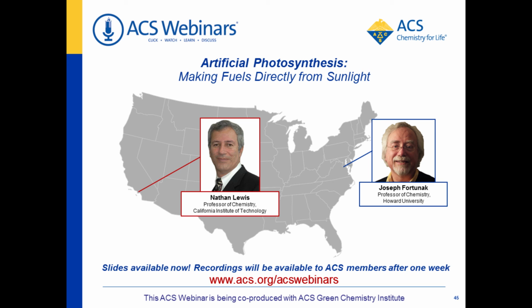Okay, I think we probably have time for one or perhaps two more questions. One from Alyssa Rosas is, what's the current density at 500 millivolts over potential for the entire cell? That's a very good question. So right now in alkaline media, the current density at 10 milliamps per centimeter squared for the water oxidation catalysts are about 320 millivolts. And for the hydrogen evolving catalysts are under 100. So keeping score, we'll call that 400. And we keep IR drops in our system design down below 100. So we're 500 millivolts total over potential in our system.